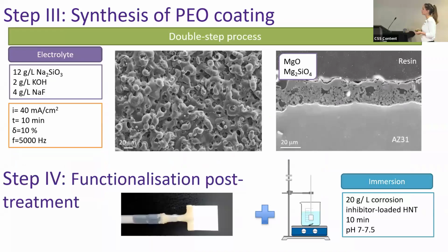So that's why we decided to try the second approach, the double-step process. So here we synthesize the plasma electrolytic oxidation coating using a silicate-based electrolyte, and then we carry out the functionalization using a simple immersion treatment. Here we can see the microstructure of our coatings.